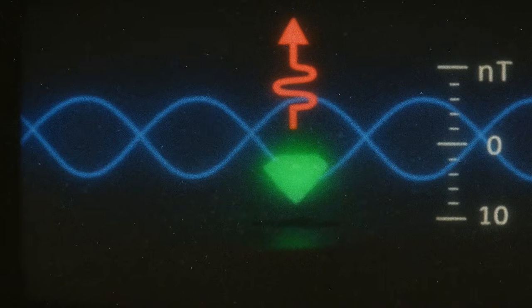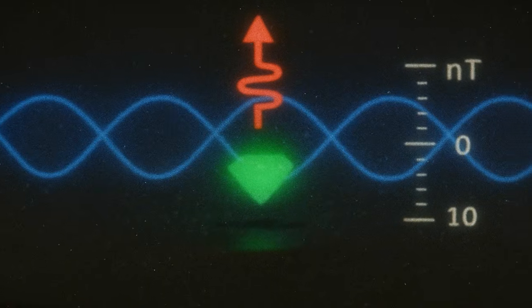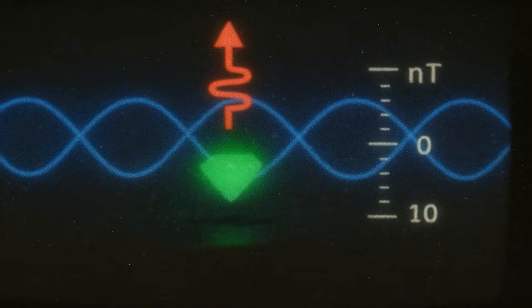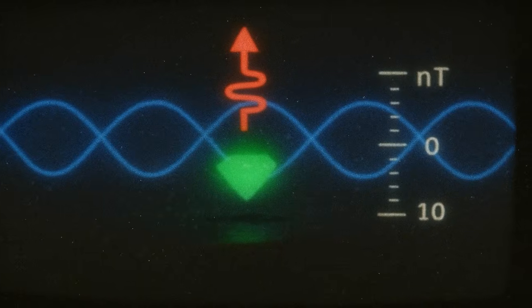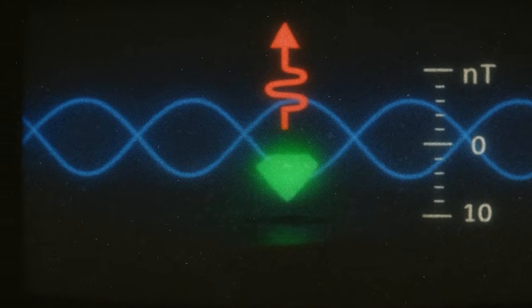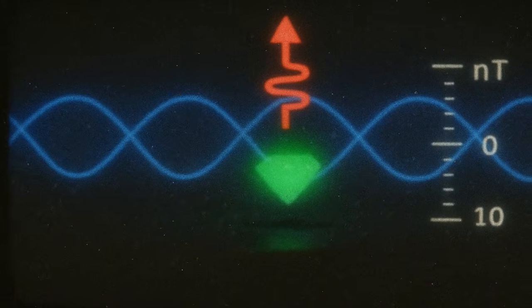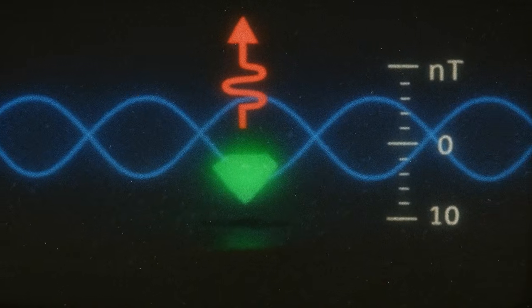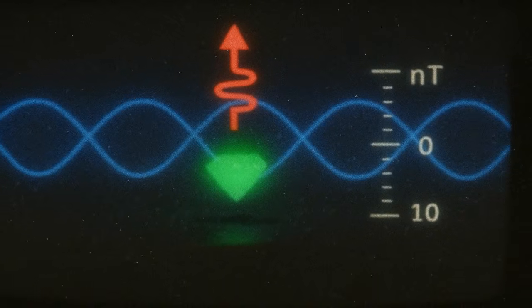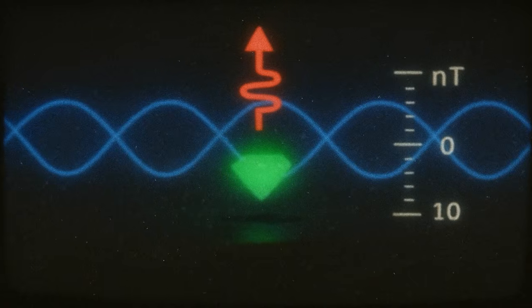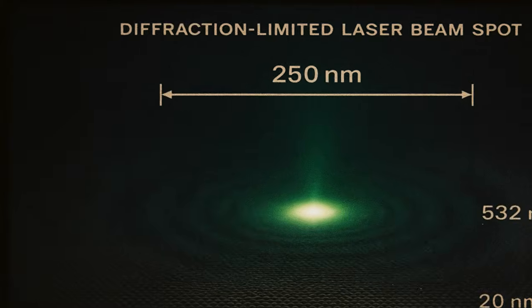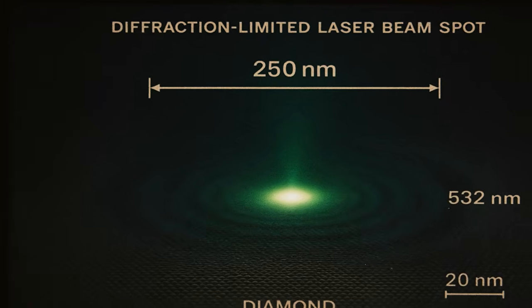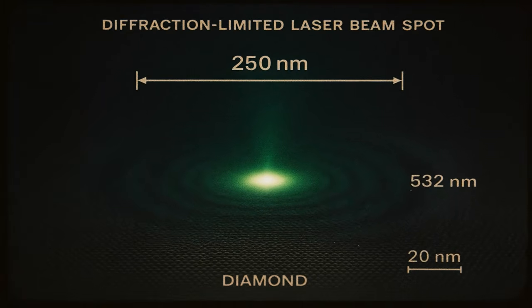The triplet excited state has a decay pathway through a singlet manifold. That singlet pathway is spin selective. M sub s equals plus or minus 1 states are more likely to take the singlet route. They end up back in the ground state without emitting a photon. M sub s equals 0 almost always emits. So after a few cycles of excitation, most NV centers sit in M sub s equals 0. That's optical initialization. Efficiency above 95%.